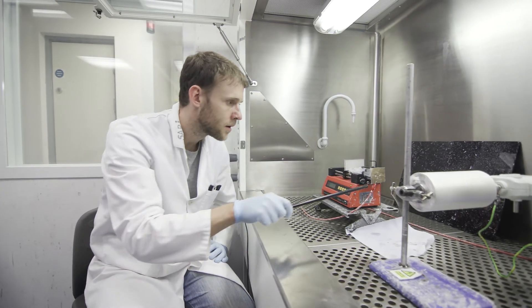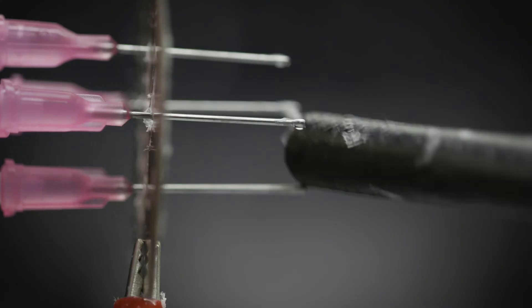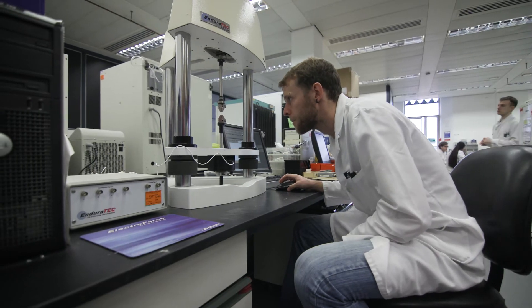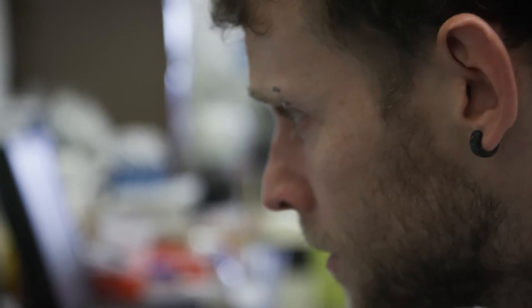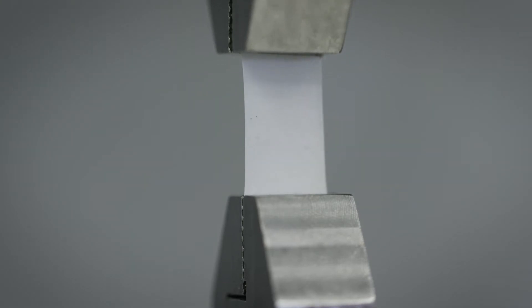I am a cell biologist working on the team. We start by producing the materials using the electrospinning technique, and with this we obtain materials with a microstructure much similar to the native pelvic tissues, while the current clinical materials have a very different macrostructure. We are also looking at the regenerative potential of patients' stem cells, which can be isolated from subcutaneous fat. The cells can then be combined with the biomaterials we develop and implanted back into the patient to stimulate regeneration. The material we have developed can be stretched and bounces back, which suits the dynamic environment of the pelvic floor tissues.